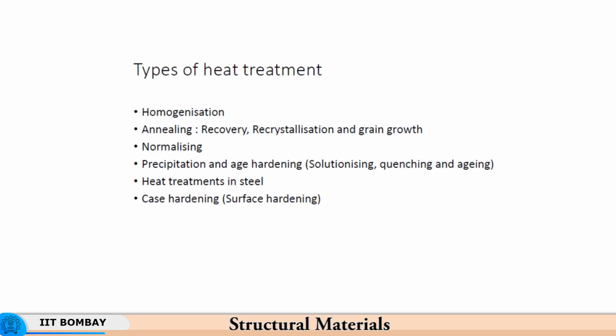So, this is called aging, and when this aging takes place, these precipitates are relatively hard particles which would refuse to deform. Again, these precipitates can be coherent, semi-coherent or non-coherent, and depending on the crystal structure, the extent of match between the matrix material and the precipitate will be determined, and this mismatch also contributes to the strength. So, now you have a precipitate which has come out; it is usually harder, with much greater mechanical properties, and it cannot deform very easily. The crack cannot pass through it very easily, the crack may circumvent it. If the precipitate has a very good interface with the matrix material, then even that circumventing becomes difficult, and that is how you find that the material behaves much harder.